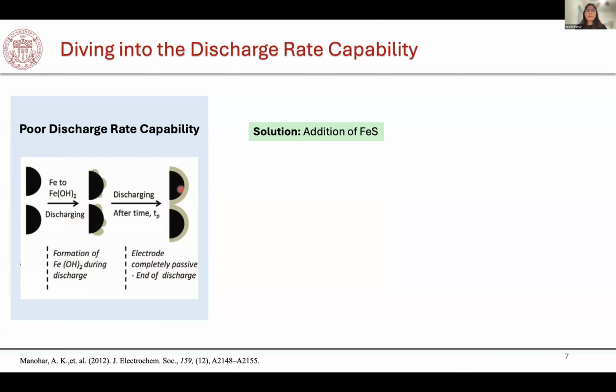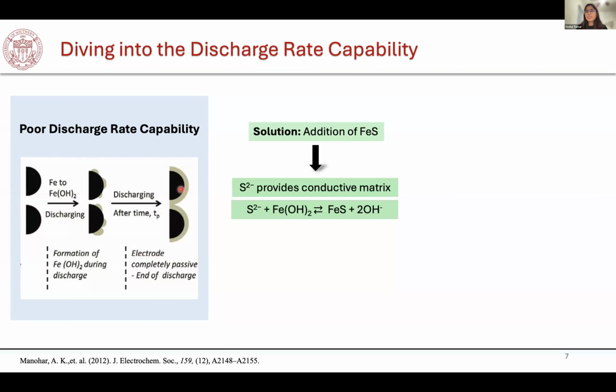In literature, people found that just adding a small amount of iron sulfide, like 5% of the electrode weight, would greatly reduce this disadvantage. So what was this sulfide doing? It was providing the conductive matrix, and the sulfide would also react with this insulating iron dihydroxide to produce iron sulfide. However, there is a certain challenge with this additive, because of which we wanted to look for alternative additives, and I will explain just now what is wrong with it.